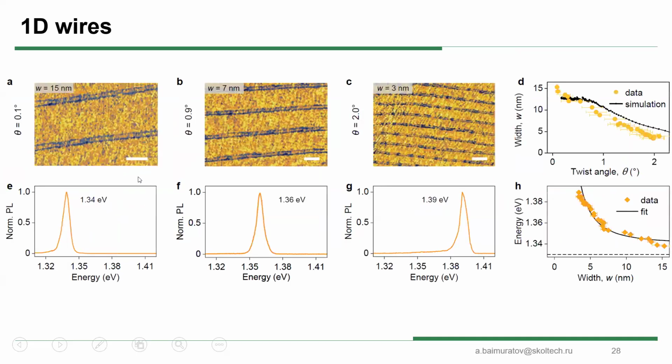Good. Yes, and we had the possibility to measure many samples, and we found that the distance between these two walls depends on angle. You see that it ranges from around 5 to 15 nanometers, and in principle you can change your confinement, and we prove that.